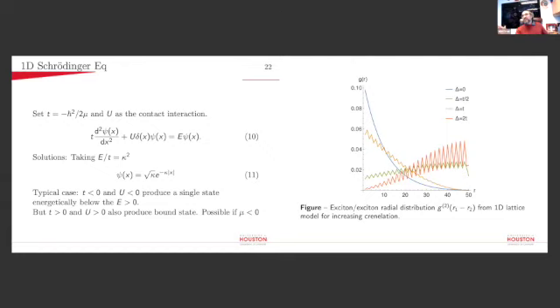Carlos had a really interesting point that maybe I didn't appreciate at the time, and we hadn't thought about it in this framework. If you think about T as the prefactor for the kinetic energy operator in a one-dimensional Schrodinger equation, you can wonder about this strange result. Here's a one-dimensional Schrodinger equation for a delta function potential. If I take T as minus h bar squared over 2 mu, the reduced mass, so long as T and U have the same sign, I still get a bound state, meaning that the bound state wave function decays exponentially away from the contact potential. The sign of U and T doesn't matter as long as they're the same sign. You get a bound state, an exponentially decaying state.